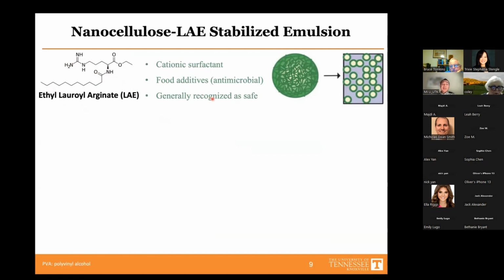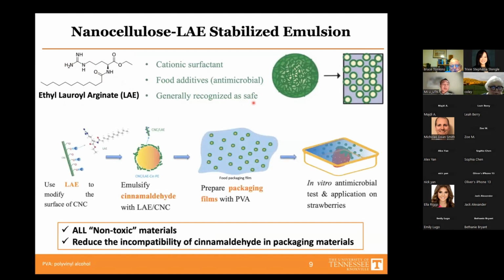This chemical is generally recognized as safe in the food industry. So the idea is that nanocellulose usually bears a negative surface charge, and we apply this chemical, LAE, to interact with the surface, using the positive charge of the head to modify the nanocellulose, and then to control the charge of the nanocellulose in order to control the packing density on the interface. The other thing it brings is that this LAE chemical has a hydrocarbon tail that can interact with the essential oil because they are compatible with each other. So eventually, we hope this can stabilize the essential oil droplets in the system.